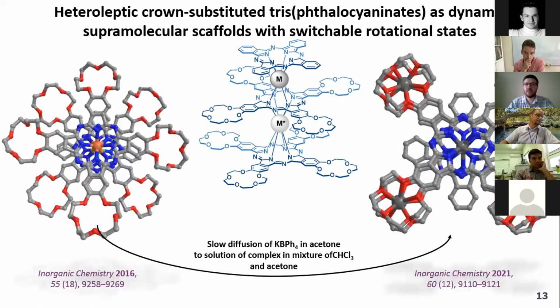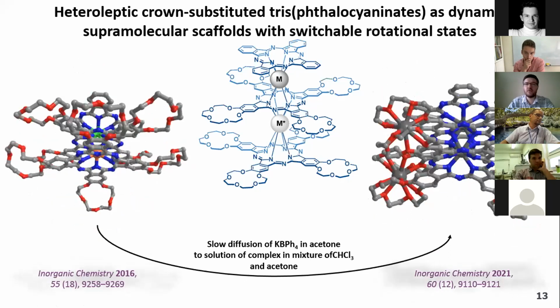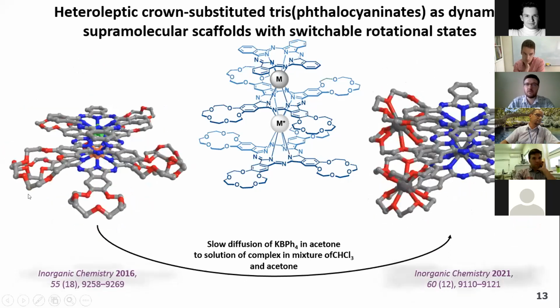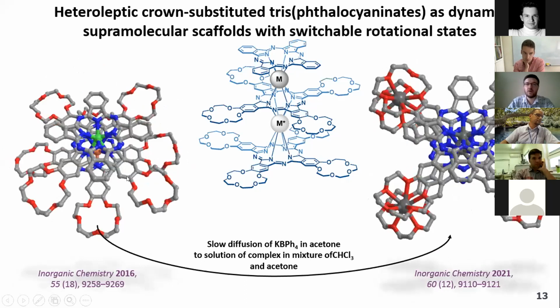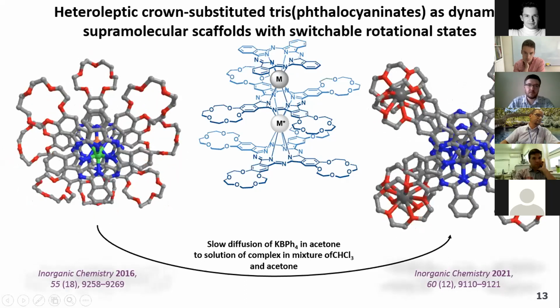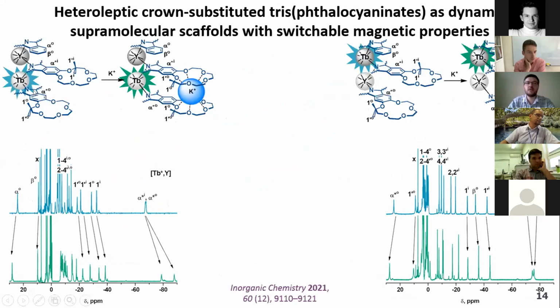So this molecule is a good object to study the influence of coordination polyhedron on magnetic complexes. With this aim, we performed NMR titration of two different heteronuclear complexes, with switchable and non-switchable terbium ions, with potassium tetraphenylborate. So we used NMR spectra, and we saw that in the case when we observed switching, shifts of resonance signals of different protons were observed.